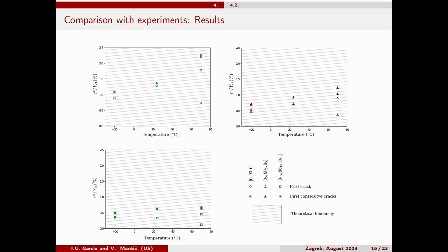So we are plotting here for the 3 thicknesses: the first is the thinnest, the medium, and the thickest laminates. In horizontal, we have the temperature of the experiment, and in the vertical axis, we have the strain level at which we detected the first crack onset. We are actually plotting 2 levels of strain: one for the very first crack onset, that is the first acoustic event that we associated to a transverse crack, but also the strain level at which we have some consecutive cracks that are very close in time, because the first one can be a defect that is propagating or so on. So we are plotting the 2.